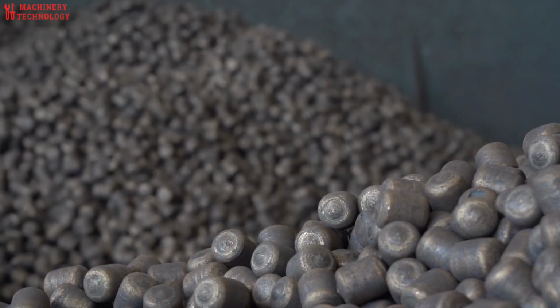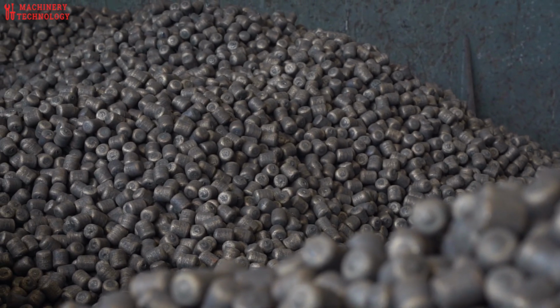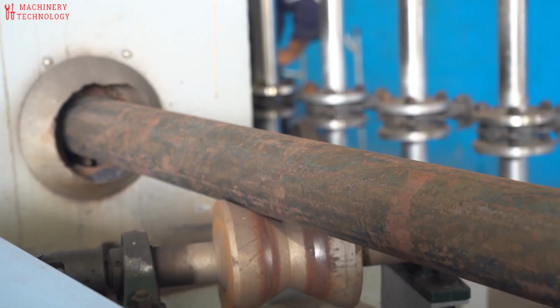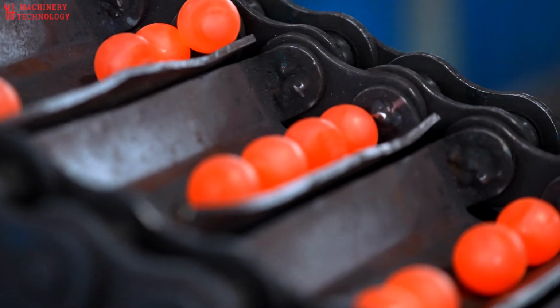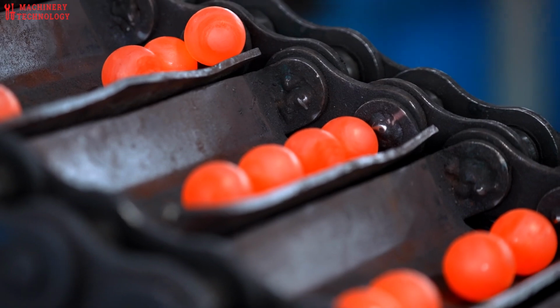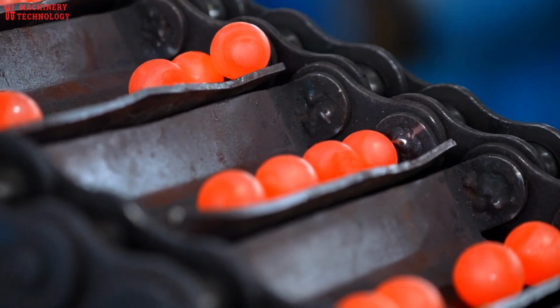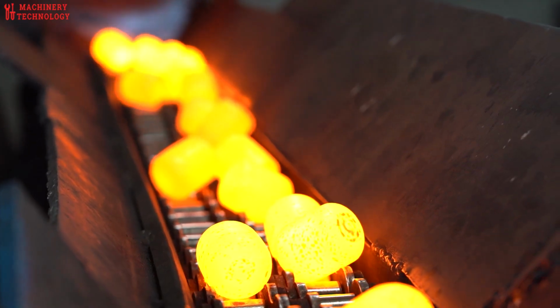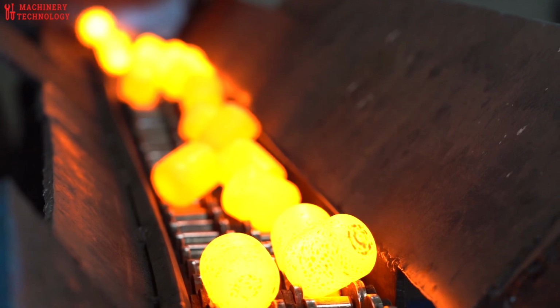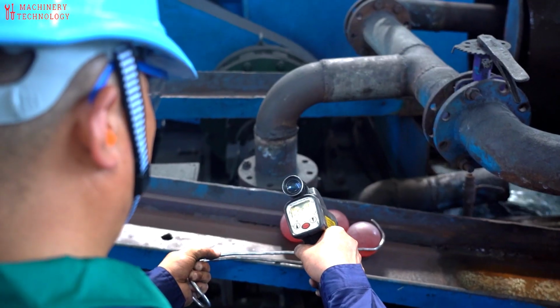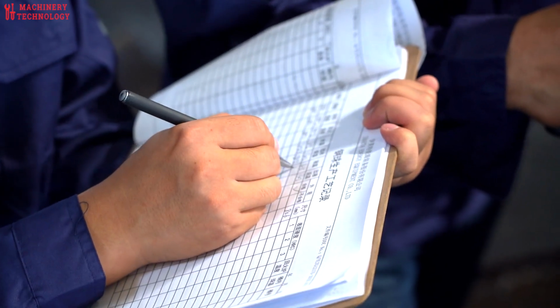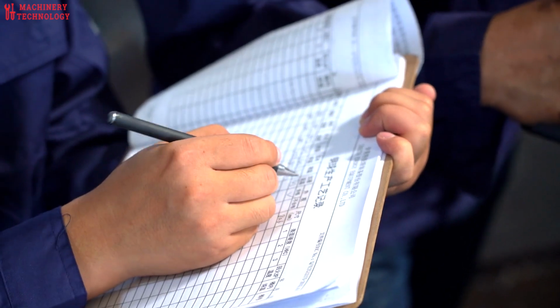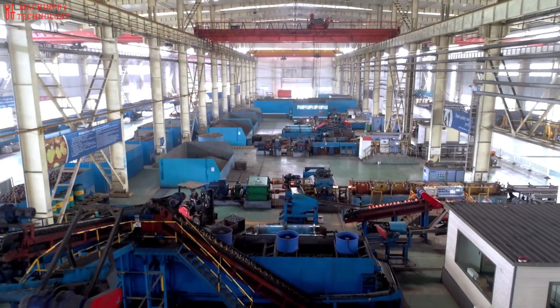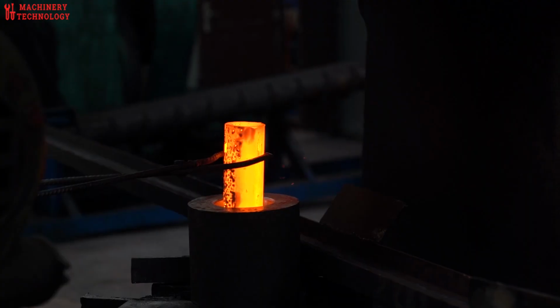Cutting. Steel rods or billets are precision cut into small cylindrical pieces, slugs, of uniform size. Automated cutting ensures consistency and minimizes material wastage. Forging. The slugs are heated in a furnace to temperatures ranging between 900 to 1200 degrees Celsius to achieve malleability. This high temperature also activates recrystallization processes, which refine the grain structure, enhancing mechanical properties.